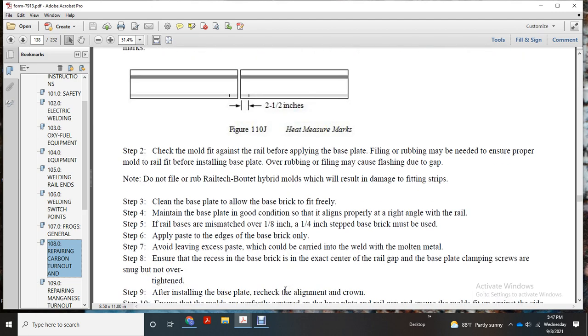Step 3, clean the base plate. Allow the base brick to fit freely. Maintain the base plate in good condition so that it aligns properly at a right angle with the rail. If the rail base has a mismatch over 1/8 of an inch, or a 1/4 inch step, a base brick must be used. Apply paste to the edge of the base brick only; avoid leaving excess paste that could be carried into the weld with the molten metal. Ensure the recess in the base brick is at the exact center of the rail gap.